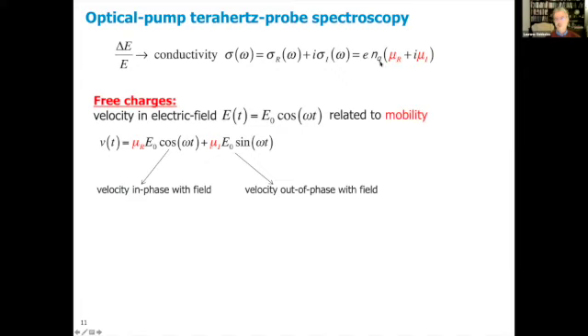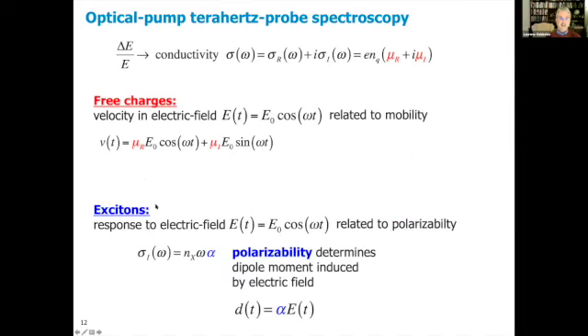So the conductivity of a material is the number density of charge carriers times the electronic charge times the sum of the real and i times the complex number, the imaginary mobility. Now, what are these? If you have an electric field oscillating like E0 cos omega t, then the velocity of charges can be in phase with this field, and the amplitude of that in-phase component of the velocity is the real mobility, but it can also be that it lags behind a little bit the motion of the charge due to scattering, and that is known as the imaginary component of the mobility. So that's the velocity out of phase with the field. And if you have excitons, then the oscillating electric field can induce a dipole moment.